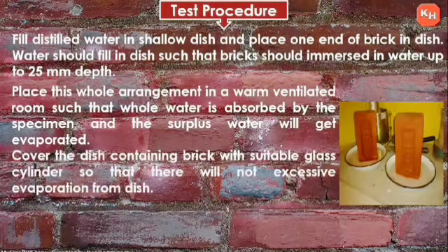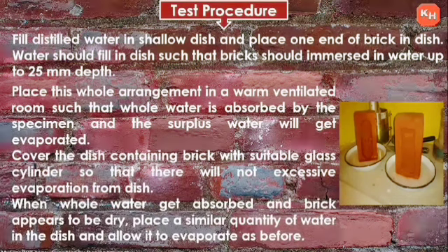Cover the dish containing the brick with a suitable glass cylinder so that there will not be excessive evaporation from the dish. When the whole water gets absorbed and the brick appears to be dry, place a similar quantity of water in the dish and allow it to evaporate as before.